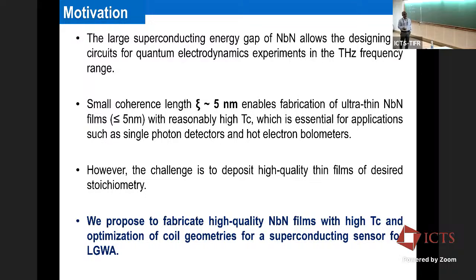However, the challenge is to deposit high quality thin films of the desired stoichiometry. This is really a cumbersome process. So we propose to fabricate high quality NbN film with high TC and optimization of coil geometry on it. Already, day before yesterday, you sent the dimensions for the geometry, and Meenakshi is working at INRIM on developing the mask for the geometries.